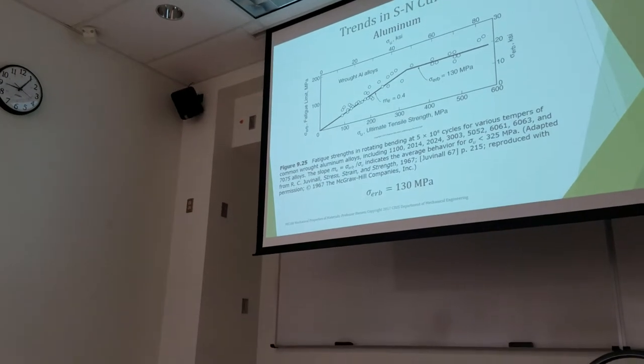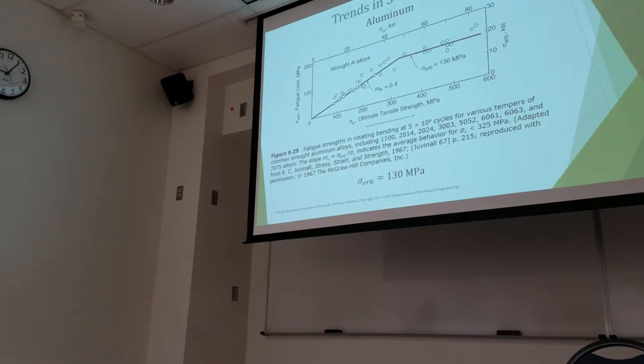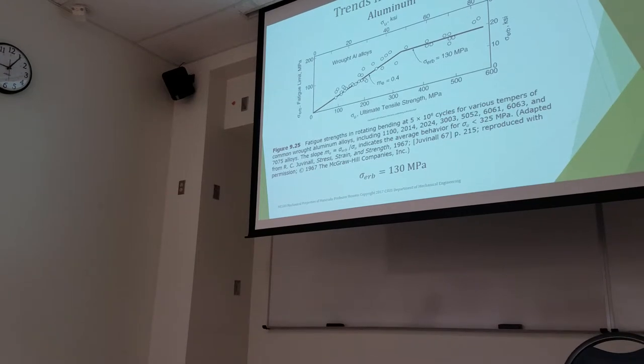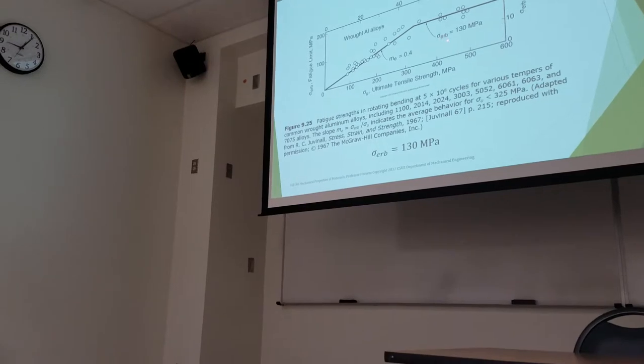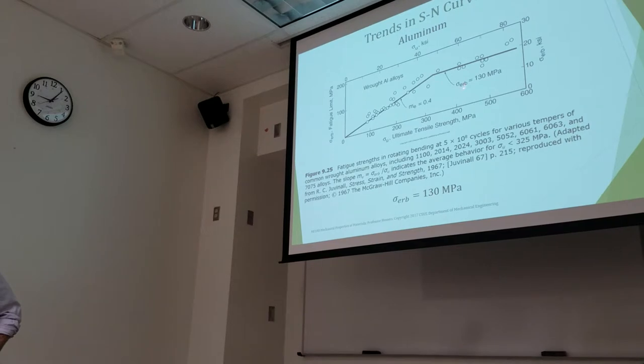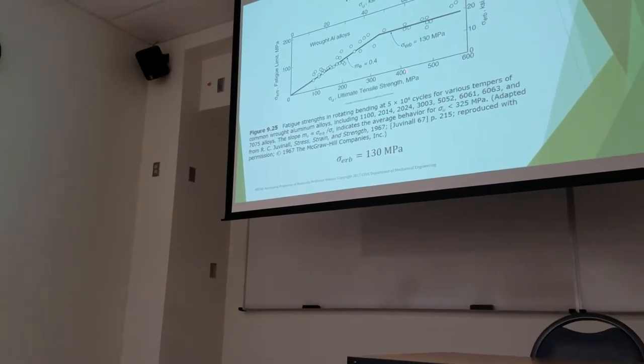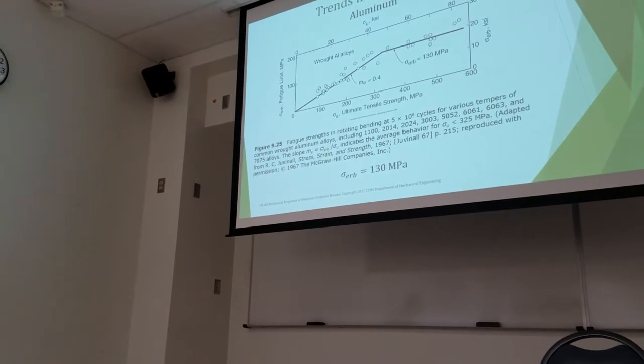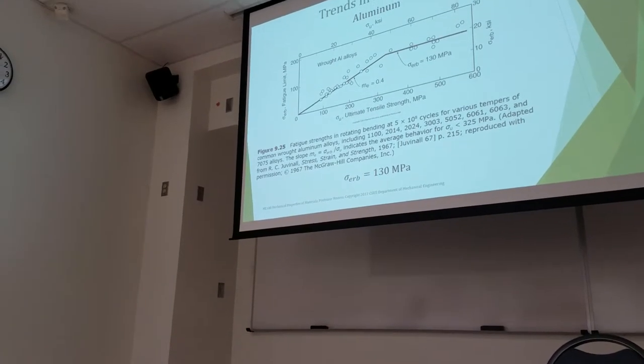We can use our endurance limit — about 40% of the tensile strength — in our design target. And then once we get up above an aluminum that has a higher tensile strength than 325, we use this sigma, this endurance limit. ERB just means endurance limit, fully reversed, and bending. So we can use this 130 megapascals as an endurance limit for any aluminum that has a tensile strength greater than 325 megapascals.